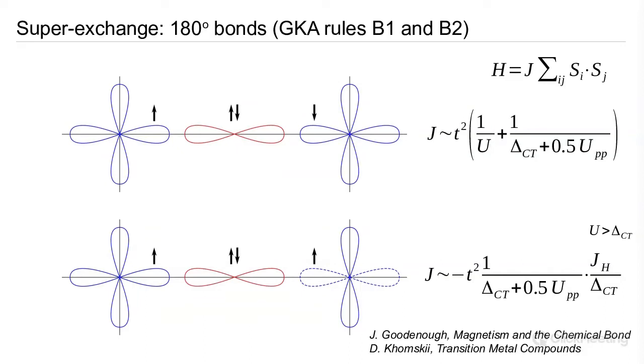And so we can concern ourselves with the excited state, and what we can show is that if, for example, the spin up electron on the oxygen can hop over to the d orbital on the right, which will be possible if that spin is down, then the spin up electron on the left will hop into its place on the oxygen in the middle here. So essentially, if we have anti-aligned spins on the d orbitals, that facilitates some degree of hopping across this bond, which ultimately lowers the energy of the system.